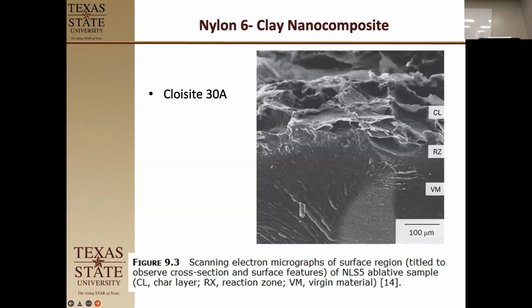Okay, so let's dig a little deeper in there. What they did here is this is the surface of 5 weight percent Cloisite 30A, and Cloisite 30A is a quaternary ammonium salt modified clay to make it easier to get into materials. What you'll see here on the top layer is the little white edges, which are the montmorillonite that's left over after the carbon stuff burns away. As we go further in, you might be able to see the montmorillonite stuck in the matrix here, but the white edges are the part that didn't burn off. It stayed there as that char layer.